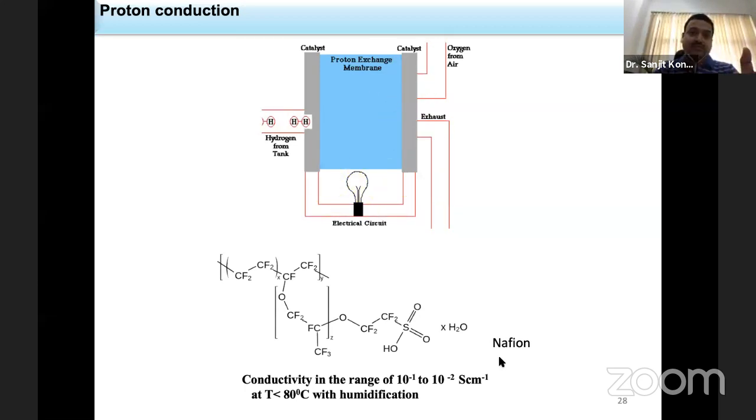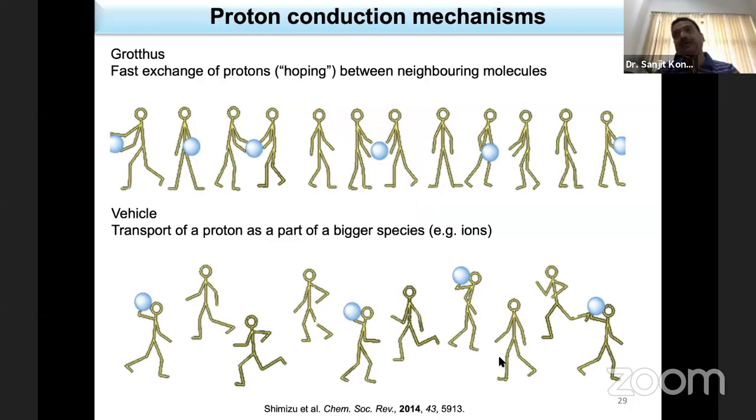So what we need, first of all, in terms of chemical design, is that in any material you should have a carrier inside the pore. Carrier means proton has to be carried. So there are two different mechanisms for proton carrier. One is called the hopping mechanism, means you have a carrier for H plus, so H plus can be given from one molecule to another molecule, to another molecule, to another molecule. So it has to be connected, the carrier should be connected via hydrogen bonding in a one dimensional channel.